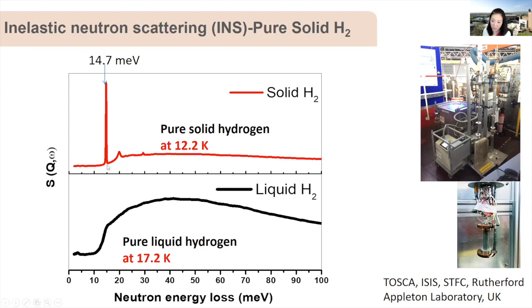And then we found this sharp, significant peak at 14.7 meV. That is the characteristic peak for solid hydrogen collected at 12 Kelvin. And if we heat the system up to 17 Kelvin, the solid hydrogen melts to the liquid phase, and we can see this characteristic peak broadened and flattened. So it became a big bump. And if we continue to increase the temperature to gaseous hydrogen temperature, the curve becomes completely flat.